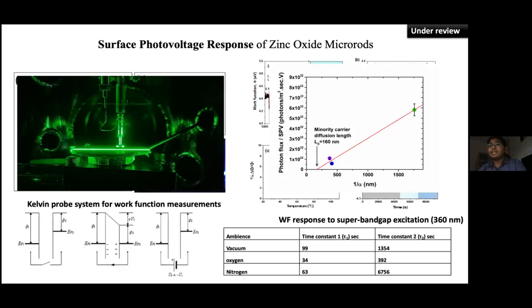So effectively it is very useful for solar cells, photovoltaics and photosensors, because once these photo carriers are generated, for a solar cell you want to extract that charge and you don't want to lose it in recombination. So you want to optimize the thickness of the sample within the diffusion length of the minority charge carrier, such that it is extracted by the electric field or the open circuit voltage that you are measuring.